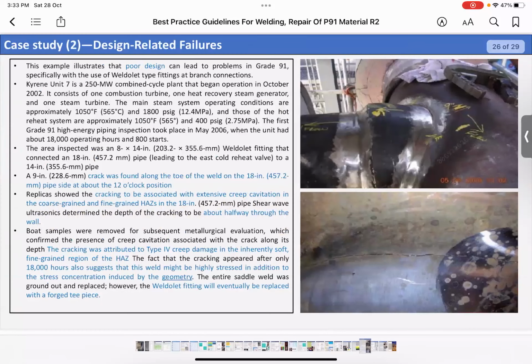The second case is related to improper design. That was a poor design, a weldolet welded to an 18-inch pipe, and the crack was in the 12 o'clock position. Cracking was associated with extensive creep cavitation in the coarse grain and fine grain area, as we'll see in the photos, and it was about halfway through the wall.